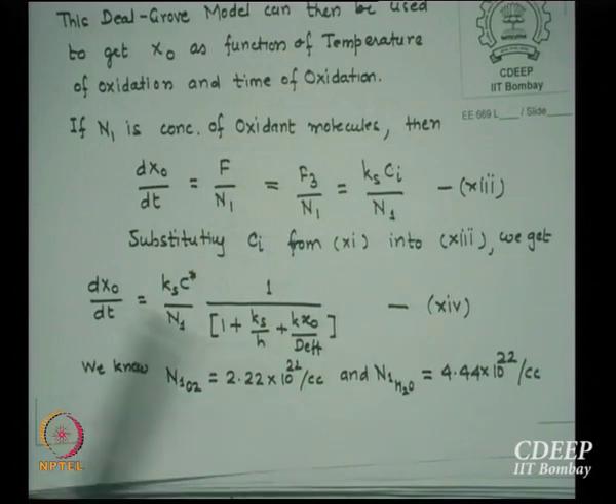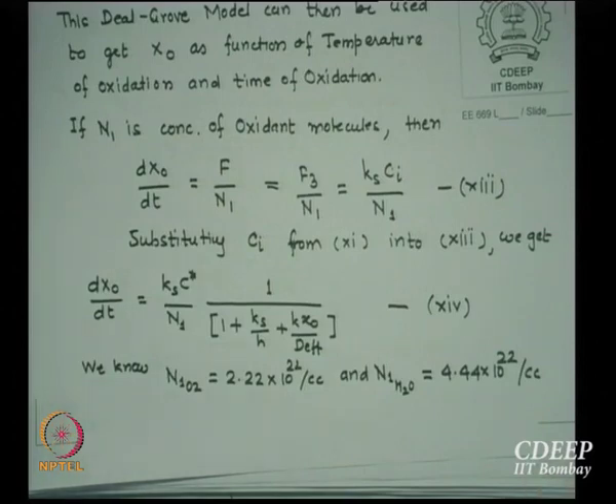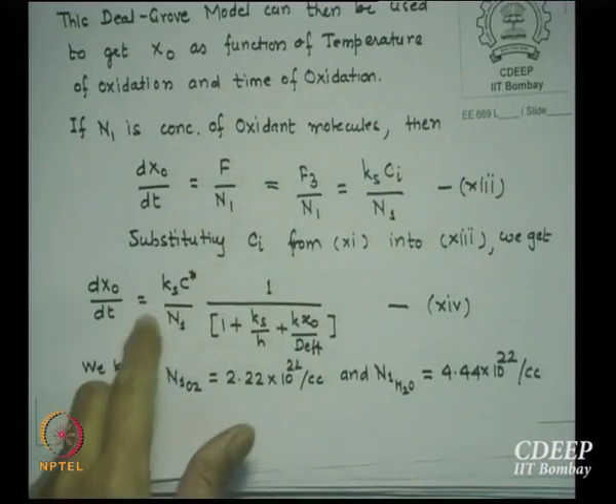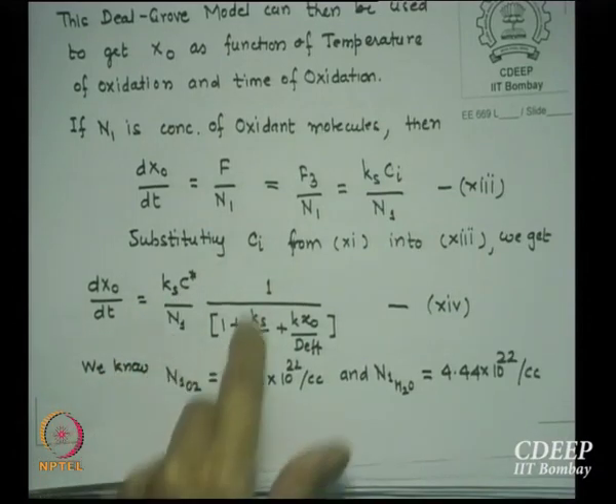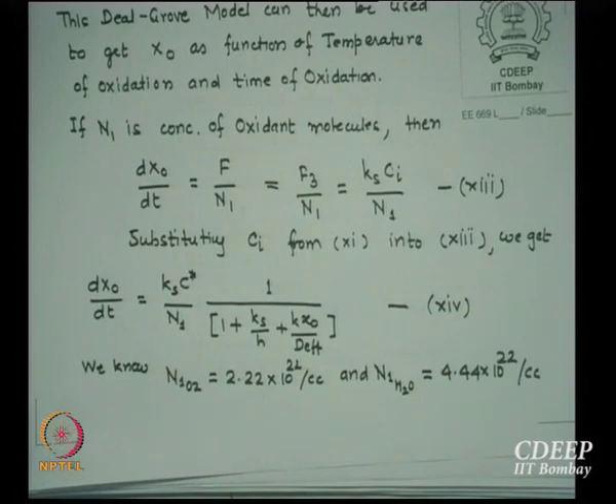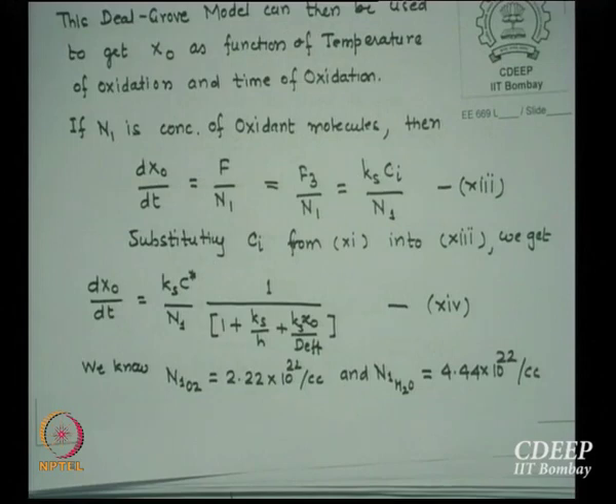So dx0 by dt equals KsCi by N1, and I substitute Ci from the last equation, the expression for Ci I just derived. So substituting Ci here, it gets Ks upon N1 times C star, times 1 upon 1 plus Ks by H plus k X0 by D effective. So how does it look? We'll get a simple looking expression for this. First you note down this.